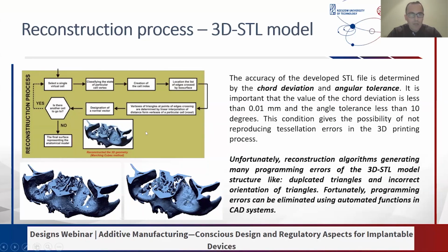using the Marching Cubes algorithm. And in this slide, I present the first choice of reconstruction. So we don't use the interpolation process, we choose the thresholding method, and the final representation looks like this. When we choose the interpolation process and the random forest segmentation method, we have more area that is reconstructed in the mid phase of the patient. If we choose the Marching Cubes algorithm, it creates programming errors. But there is no problem because we choose the automated function in a CAD system that decreases the influence of these errors.